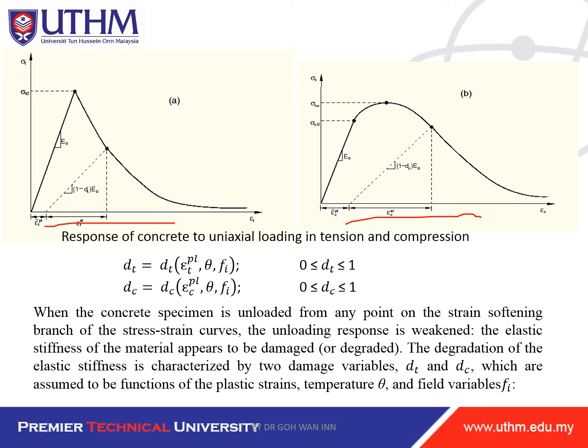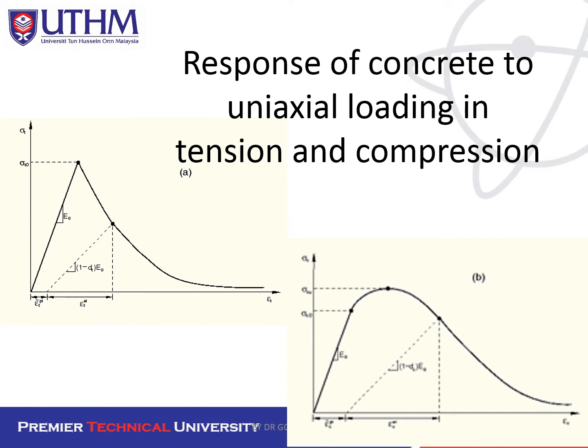This shows the response of concrete to uniaxial loading in tension and compression. From the split tensile test, you apply load on top with support at the bottom and the specimen splits. The test only records data up to the ultimate strength, so what we have to do is mirror the result — mirror the stress values from that part to obtain the softening branch, and similarly handle the displacement.